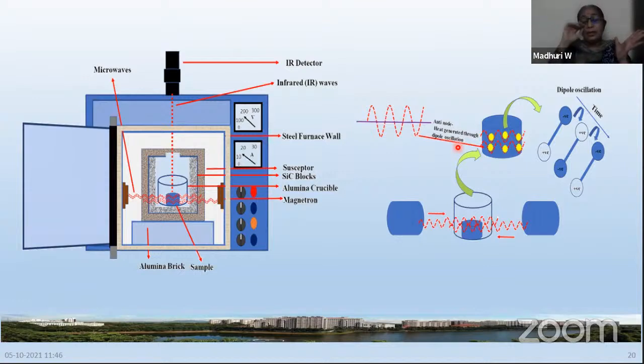If you are conventionally sintering a ferrite at around 1200 or 1250 degrees centigrade, using a microwave you can actually sinter it at a very low temperature of around 900. Microwave can sinter it at 900 itself, because the heat is being generated internally. To reach that 900 from room temperature it needs some 15 minutes, depending on the heating rate you give. Once you reach the required temperature, the soaking time you need to keep is a maximum of 20 minutes for most of the ceramics.